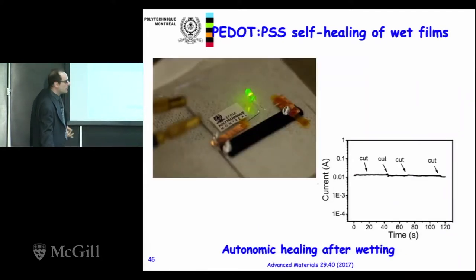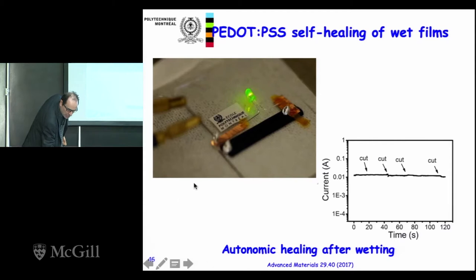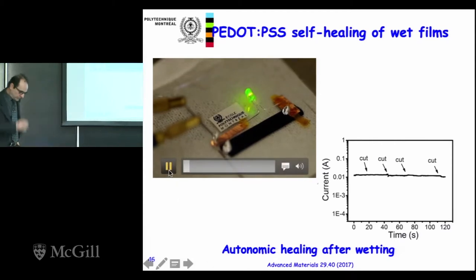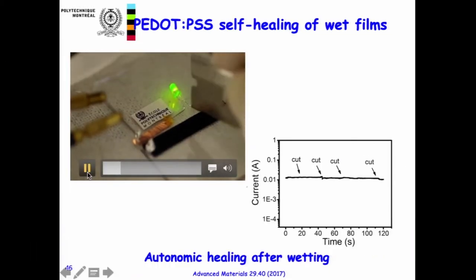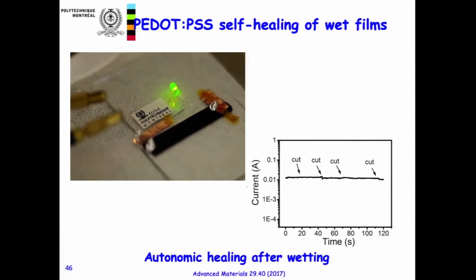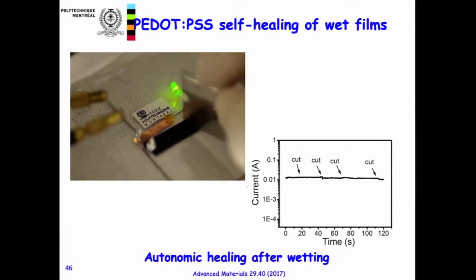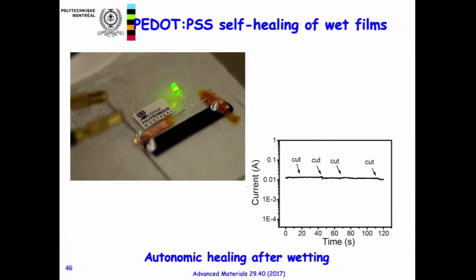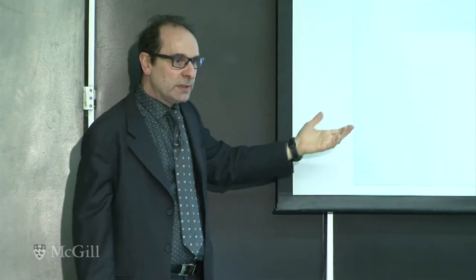Then, again, the other idea was let's wet the materials before cutting them. And you see what happens. There is no effect. So you cut. You see also here, current doesn't change. So there is a kind of instantaneous healing of the material. Why? We still don't know, but we are probably close to finding an explanation to this. So if you have a material which is wet, it becomes a so-called autonomic healable material.